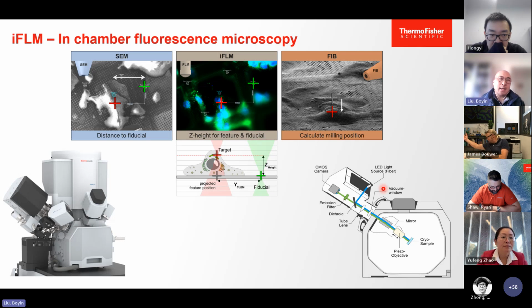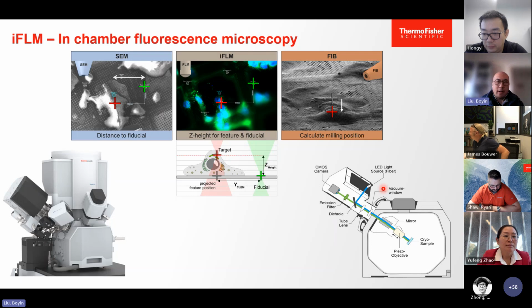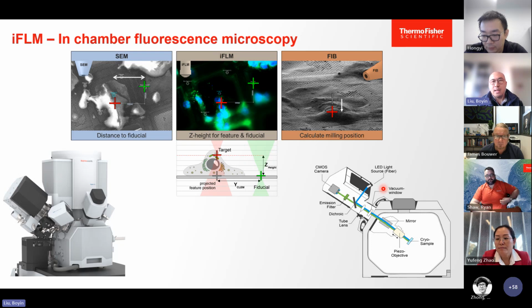iFLM is another piece of hardware on the cryo-FIB. It's in-chamber fluorescence microscopy, initially designed for cryo-tomography work. In cryo-tomography, the cells are embedded in buffer, and under the SEM there's no contrast. You can't really find your target under the SEM. So what people do is fluorescently label the proteins and then clamp in the SEM chamber and find the target to mill.